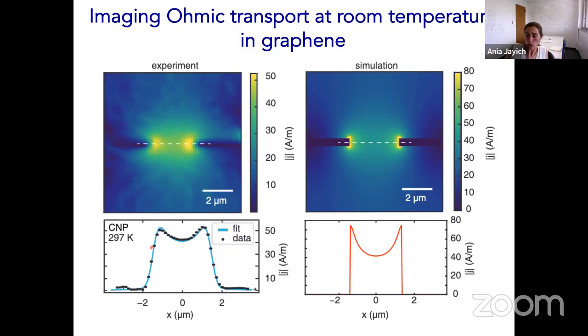I showed you previously that through simulation, one expects the current profile to have these very sharp features. The reason we don't see these very sharp features is because this simulation is actually convolved with the point spread function, the fact that our NV center is a few hundred nanometers away from the device.